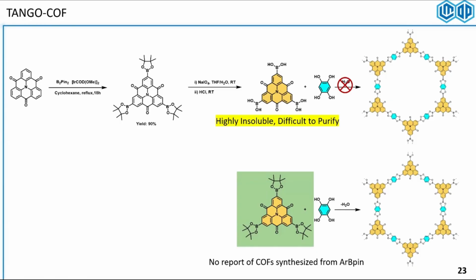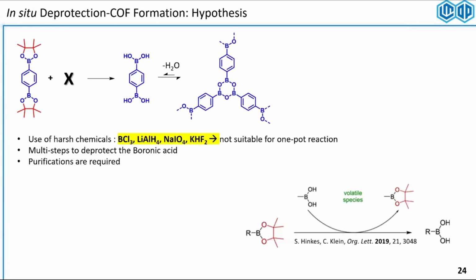So the idea was, why not take this protected boronic acid and form a COF with it, right? No reports at the time, for very obvious reasons if you know boronic ester condensations, because this B-pin is very, very thermodynamically stable. It's difficult to get it off and install another sort of catechol or diol moiety on top. So I was looking for different reactions that in principle, we would add something in there that can take the B-pin off for us. B-pin is this red group over here. And we would be able to release the boronic acid and in situ form a polymer. That would be the ideal scenario, because we didn't want to get the boronic acid separate and purified.